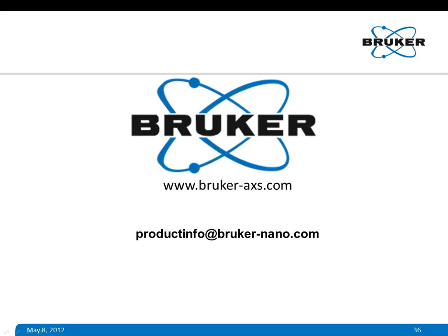You can also attach an acoustic emission sensor to see if at all any acoustic emission comes from the failure of the coating. But most likely this is a polymer, and I have found that in polymer it is very difficult to get good acoustic emission signal. Probably you may not get it, but it's good to try it. But ECR definitely will show. And if the acoustic emission signal is really good, probably you do not need ECR, and you can do conventional scratch testing using a Rockwell diamond stylus, 200 micron tip radius. I presume that your coating thickness for this epoxy system will be really thick, maybe 30, 40, 50 micron, maybe 100 micron. You can really perform the scratch test using a diamond stylus with 200 micron tip radius.